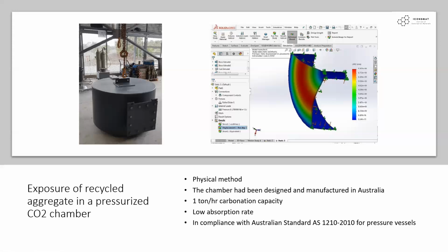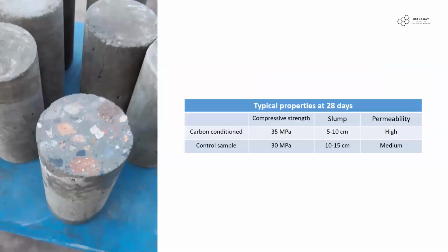How effective this method is a question that came into mind before we get into the chemical approach. The fact is that most of the injected gas immediately escapes as soon as you unseal the cap. It is claimed that 10% of the injected gas is absorbed by the aggregate. And the fact is that the bond energy between oxygen and carbon within the molecules of the carbon dioxide is so high that a low 150 kilopascal cannot simply break this covalent bond. That 10% absorption is most likely happen due to the hydration reaction and the physical entrapment of CO2 gas inside the microstructure of the aggregates.